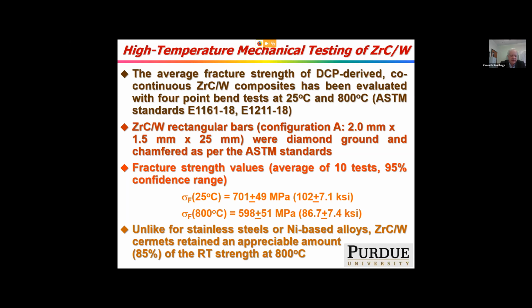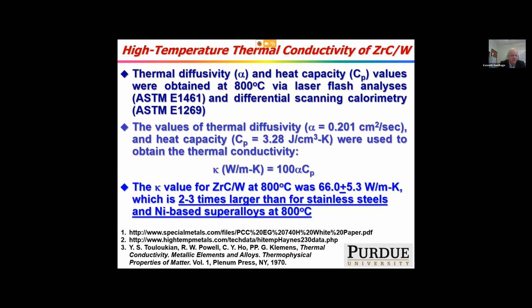So unlike stainless steels or nickel-based alloys, where the failure strength dramatically drops when you go up in temperature, we retain 85% of the failure strength of these materials at 800 C. The thermal conductivity is also quite attractive. We went to the Edward Orton Ceramic Foundation, had them measure the thermal diffusivity and the heat capacity using laser flash and differential scanning calorimetry, respectively. You can use those two numbers, of course, to calculate thermal conductivity, which turns out to be 66 watts per meter Kelvin, and again, 2 to 3 times higher than for conventional stainless steels or nickel-based superalloys that are used in printed circuit heat exchangers.